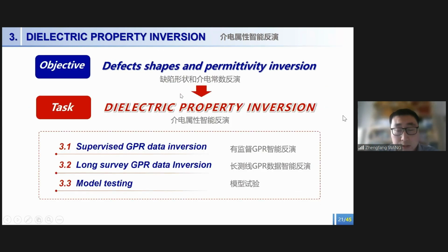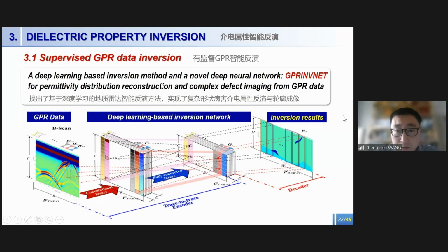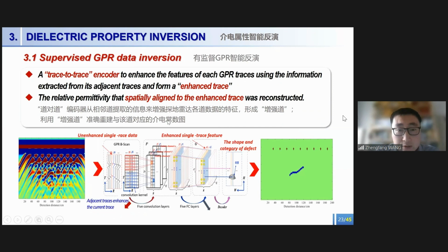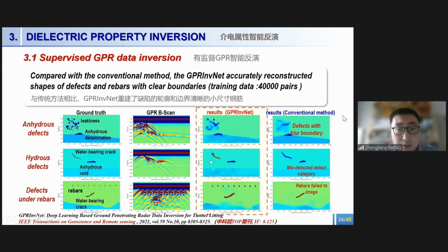In order to solve this issue, we developed some deep learning-based dielectric property inversion methods. Firstly, we developed a deep learning-based inversion method and designed a new deep neural network. We call it the GPRInvNet for permittivity distribution reconstruction and complex defects imaging from the GPR data. Specifically, we designed a trace-to-trace encoder to enhance the feature of each GPR trace, using the information from its adjacent traces, and form what we call an enhanced trace. With this enhanced trace, the relative permittivity that is spatially aligned to the enhanced traces was accurately reconstructed. The simulation validation result demonstrates that our method can accurately reconstruct the shapes of the defects and rebar with clear boundaries.